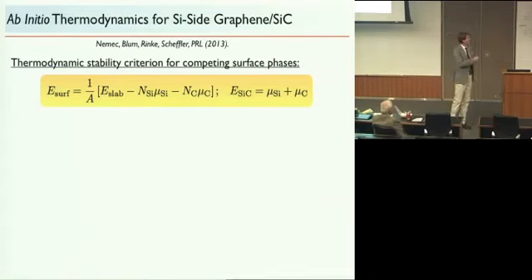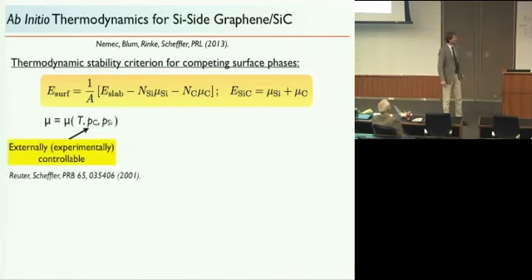There's one condition that couples those chemical potentials, which is that the bulk has to be stable, so their sum has to be equal to a silicon carbide unit cell. But the difference isn't fixed, so you get an experimentally controllable parameter, and this is, of course, the gist of thermodynamics or physical chemistry, that you can play with these things by adjusting things like temperature and pressure. This is exactly what we want to do.